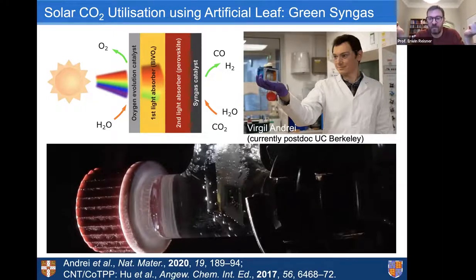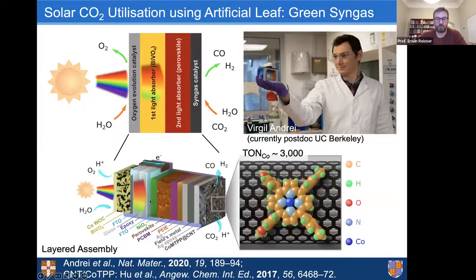And the big advantage is that this allows us to separate the hydrogen and CO from the oxygen. The disadvantage is that we build up pH gradients, and I will later on say a little bit more about that. So here are the details of this stack. The oxidative part, the bismuth vanadate with cobalt, is quite standard. What's less standard is the use of the perovskite. And the reason is that these perovskites are known to be highly efficient in the photovoltaics community, but they're also known to be extremely moisture sensitive. So in fact, to use these in such an aqueous environment, you really need to protect and seal them off so that they're not exposed to an aqueous electrolyte.